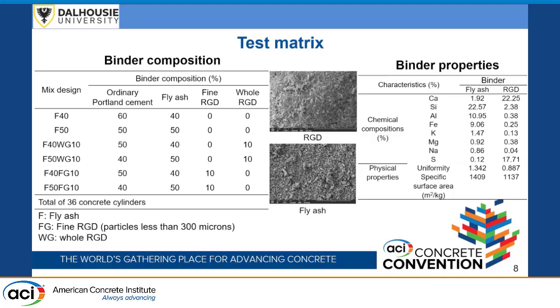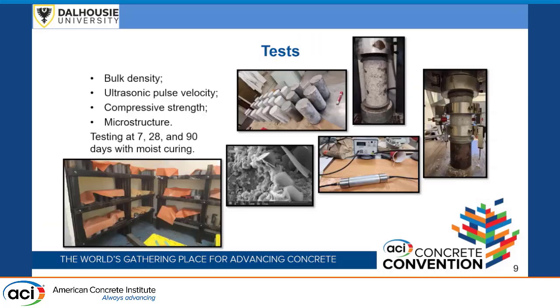So here you can see the mix design. In the mix design, we have fly ash, which is represented by F. WG represents whole gypsum, and FG represents fine gypsum. So you can see by having this mix design, we can evaluate the effect of whole recycled gypsum drywall and fine recycled gypsum drywall as both cement alternative and fly ash alternatives. And here you can see the SEM pictures of the fly ash and recycled gypsum drywall and their chemical compositions.